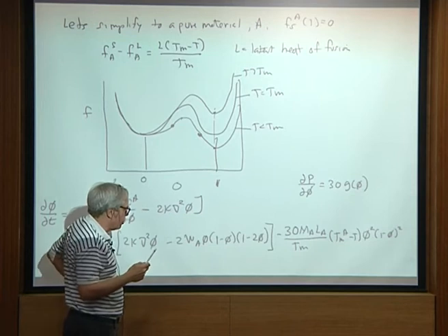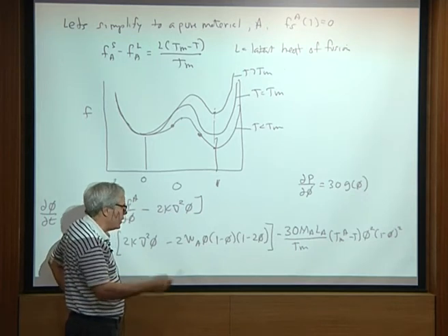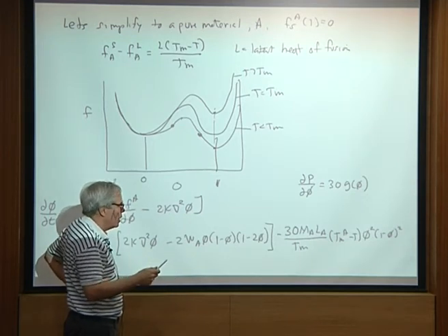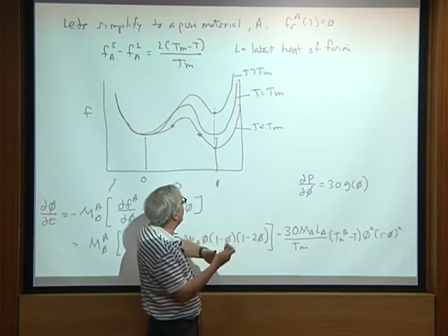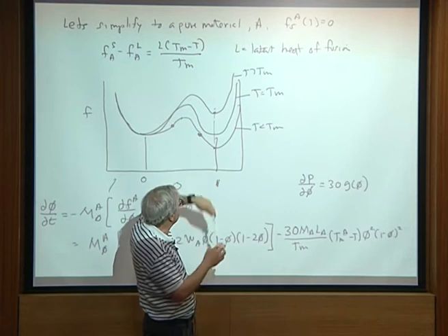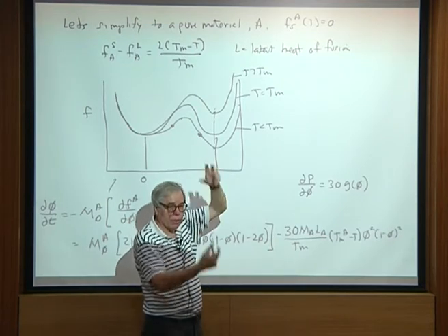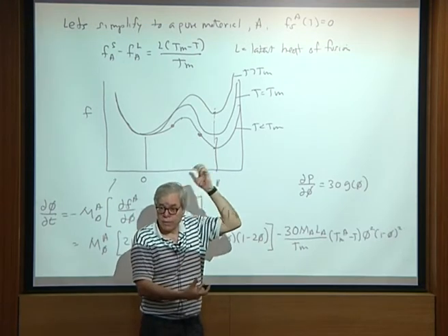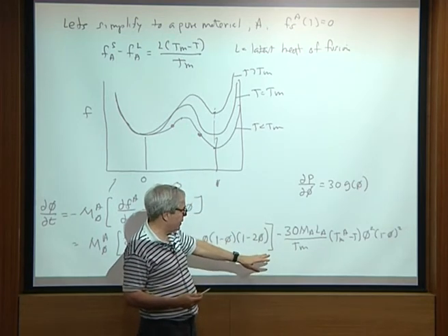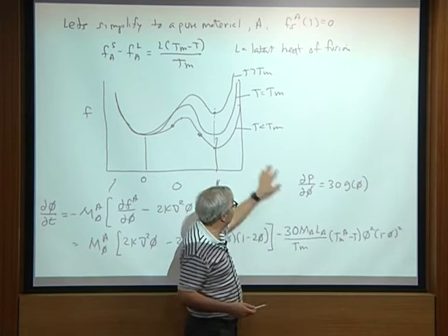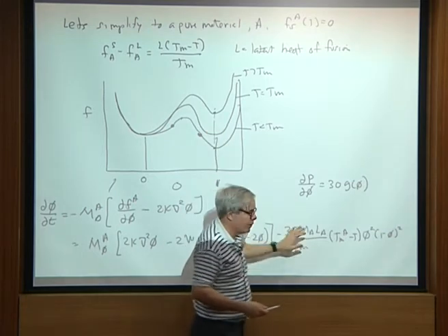And the real challenge from a phase field model is that often you don't want this mobility, but you do want the fact that this free energy function changes as you go above and below the melting point, because there are different stabilities to the phases, right? And so I'll talk a little bit about that at the end, as to how to keep this physics but get rid of this mobility effect. But mobilities are really there.